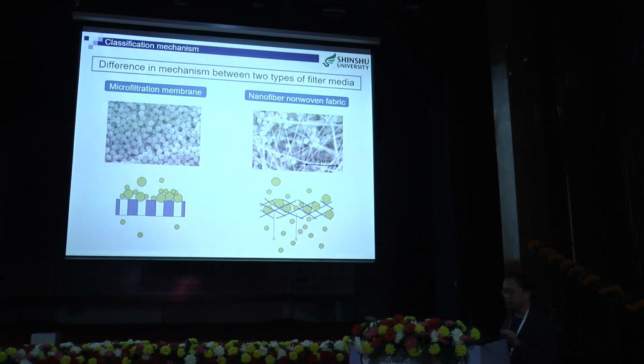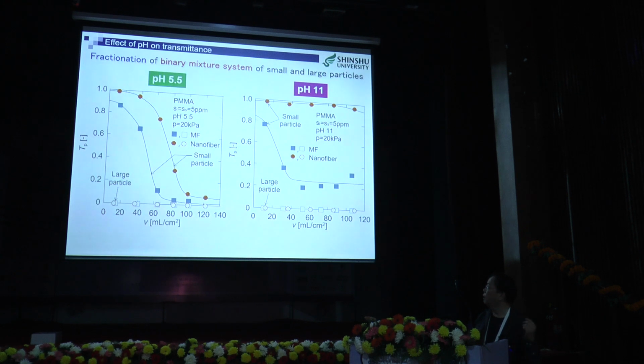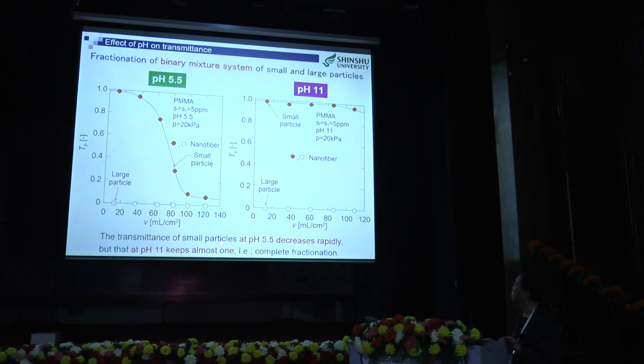Also, from the same images, we understand this mechanism. I'll get back to the previous figure. Please note the effect of pH, only pH. The transmittance of small particles at pH 5.5 decreases rapidly, but that at pH 11 keeps almost 1. It means complete fractionation. We attained complete fractionation.